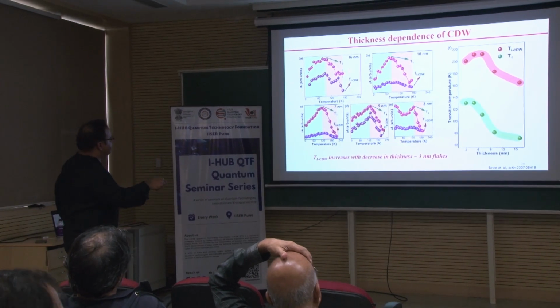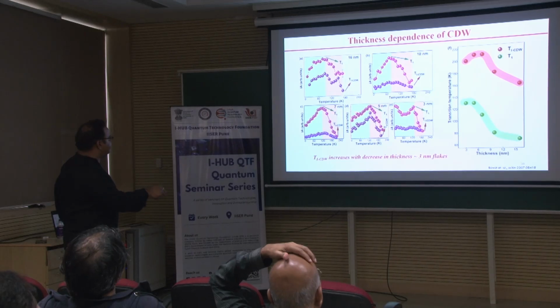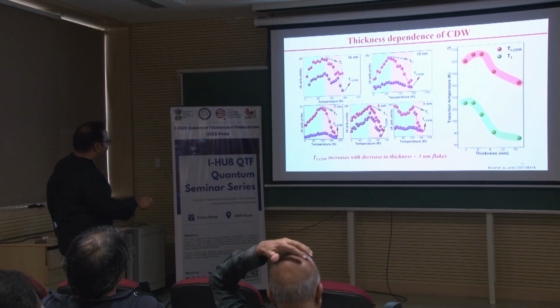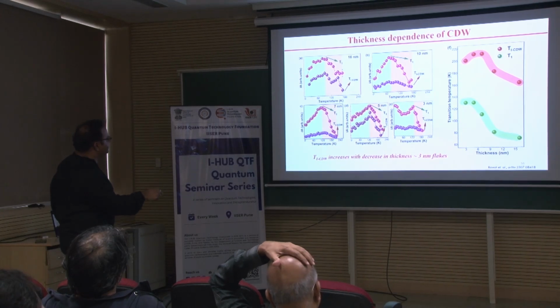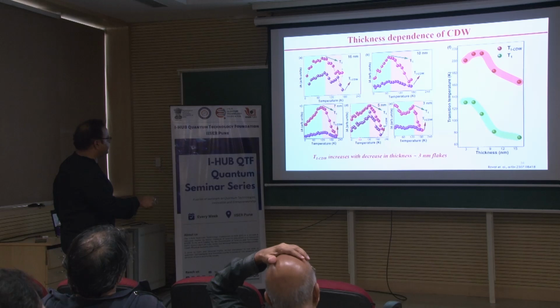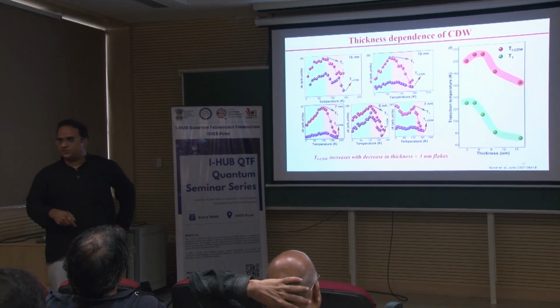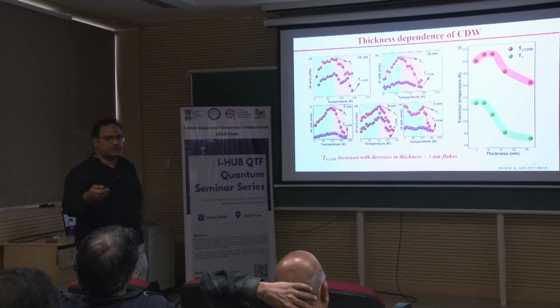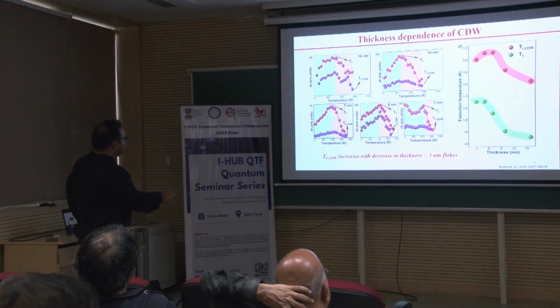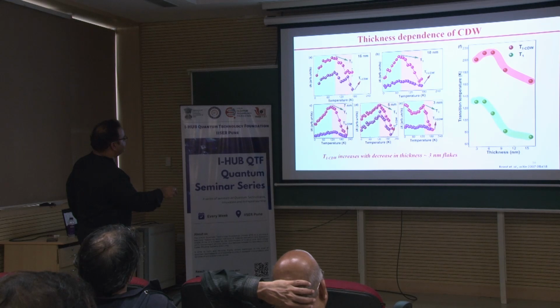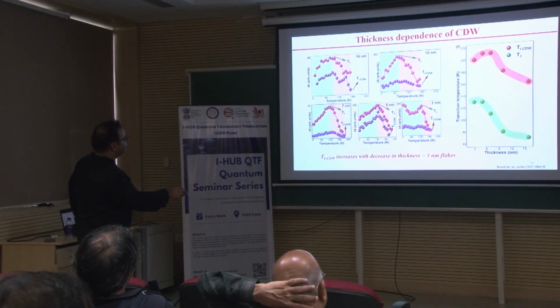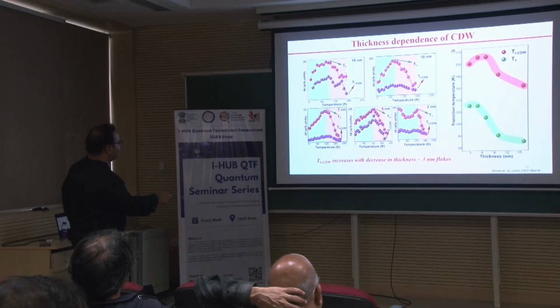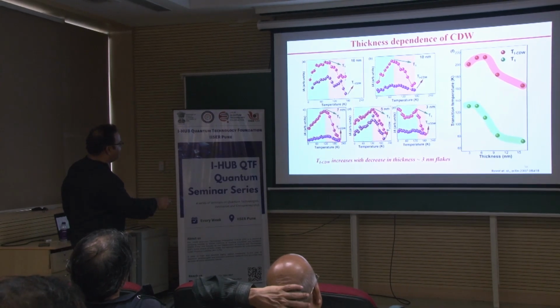So, this is 16 nanometer, this is 10 nanometer, this is 7 nanometer, this is 5 nanometer, this is 3 nanometer. Now we have a typical charge density wave region, the incommensurate charge density wave region, which I have shown you in the VSe2 also. It is going down, so you have a different kind of ordering there. We have the softening which is going even to higher temperatures. Here you can think about it, it is like 150, 160, 170, nearly 180. I am going down in the thickness, I am going up in my temperatures.